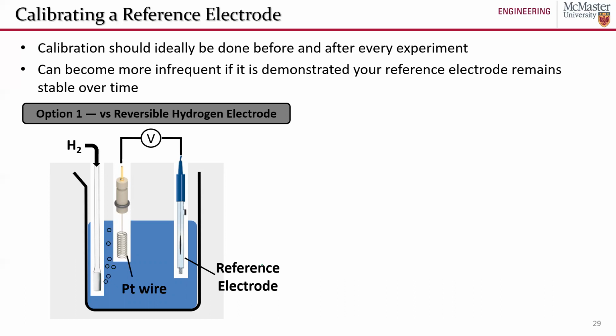It's very easy to make a reversible hydrogen electrode. I encourage all of you electrochemists to learn how to make an RHE, be comfortable with the concept of an RHE and how to actually implement it in the lab, because it's a very handy experimental tool to have in your toolbox when you're doing electrochemical measurements. So you make this homemade RHE. You stick your commercial reference electrode in that same electrolyte solution with the RHE that you've made, and then you just simply measure the electrochemical potential difference between the 2. And then you've got a calibration value to convert all of your potential measurements versus your reference electrode to the RHE scale, which is kind of the universally used scale in many fields of electrochemistry, especially in electrocatalysis, where my team works largely.